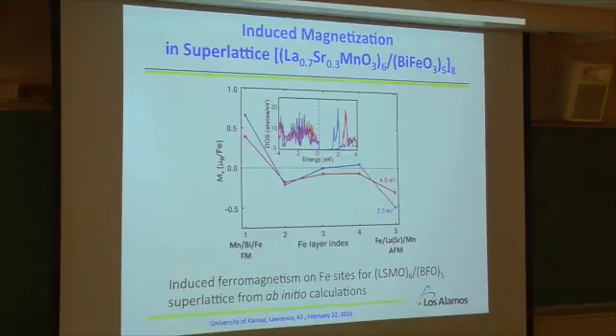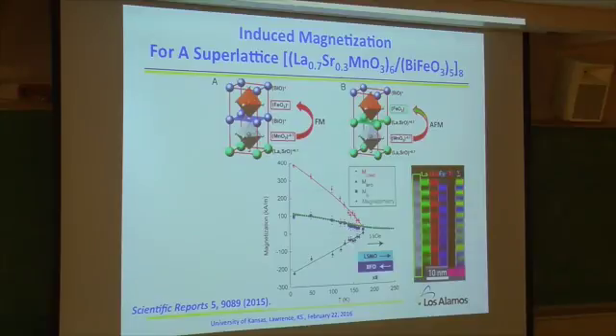Actually, when we did the calculation, we found, oh, that's interesting. We knew this part earlier, which just showed that it is ferromagnetic coupling. We said, well, is there something we can do over here or not? Interestingly, yes, you can. Here, I just show you the experimental results. Here you see this is LSMO, this is BiFeO. This is a SQUID measurement result. But over here, you see everything is negative. That's anti-ferromagnetic coupling, different from what I showed you earlier. That exactly matches the theory, okay? Which direction is your magnetization about to? Is that inclined?